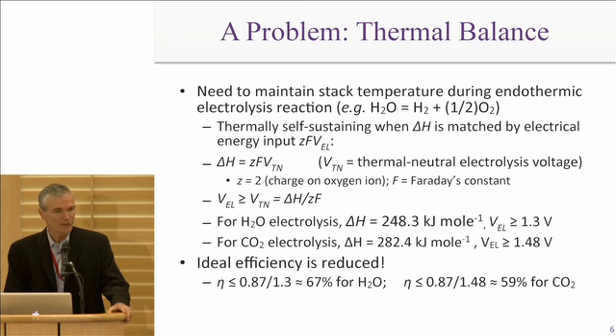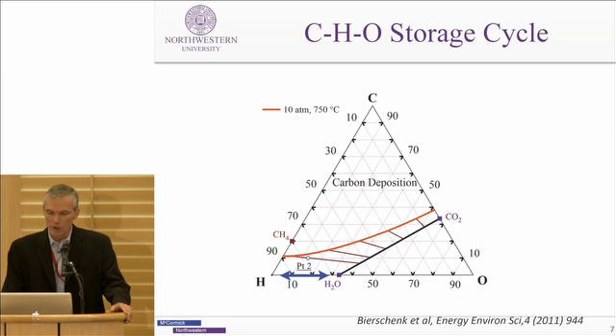Unfortunately, now if we go back to the efficiency calculations we had before, I was actually talking about operating at about 1.1 volt in electrolysis mode. Now we're seeing in reality with these reactions, you need to operate at a higher voltage, like 1.3 volts, and now your efficiency is much lower. If you do the CO2 reaction, it's even lower, like 60%. Okay? So that's really where our key innovation comes in here. Okay? So that's for simple energy storage chemistry.